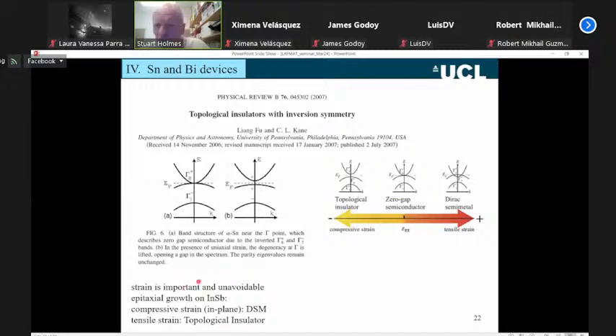It's possible to grow single crystal epitaxial tin on indium antimonide. A bit of a problem is you can't heat the material up. If you heat the material up, it changes phase into the beta phase, which is metallic. It's a non-reversible phase change. So we have to do everything at low temperatures. We have to process the devices at low temperatures.